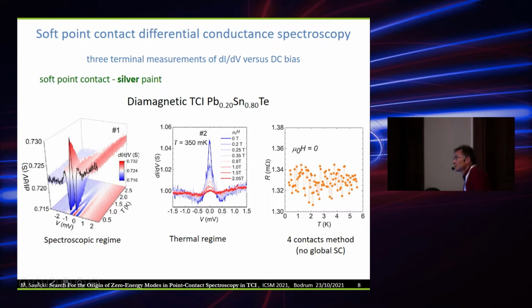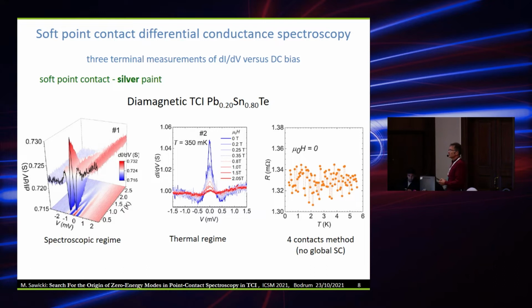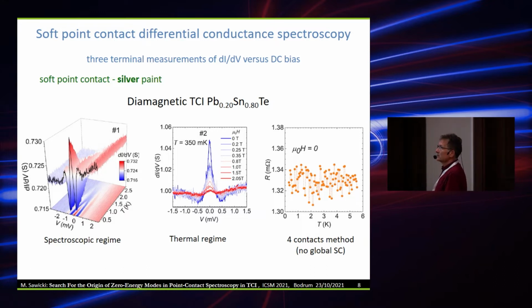So the direct 4-probe measurement of the electrical conductivity does not show the existence of a transition, the presence of superconductivity, down to the lowest temperature. The noise of these results reflects the fact that we use the lowest possible current simply not to overheat the sample, just to be able to pick up a signal that we would be able to analyze.